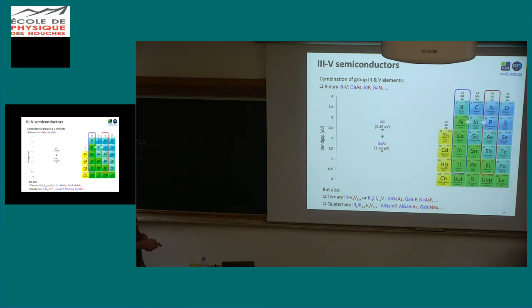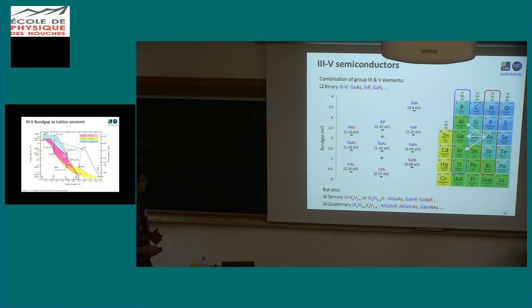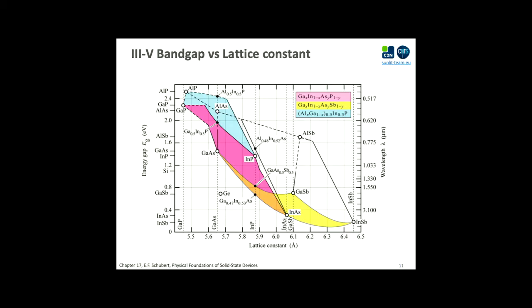What you can do also is to alloy different materials, for example, aluminum and phosphorus, and you have an even higher band gap, or you go the other way around, indium and antimonide, and you get a very small band gap. And of course, you can start to change the alloy, and you immediately have a lot of different materials with a lot of different band gaps. You can extend this and try to alloy three or four different materials, and it's getting really messy now. So what we normally do is to plot this kind of graph.